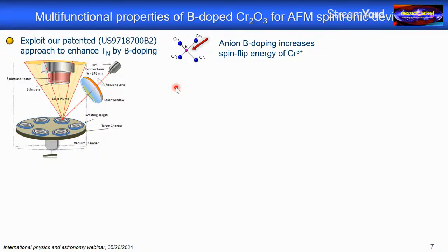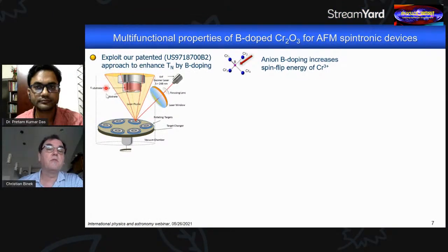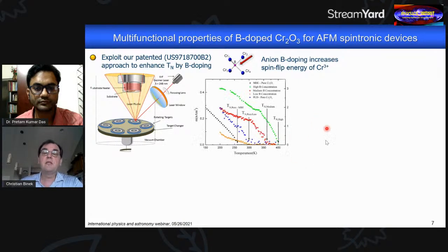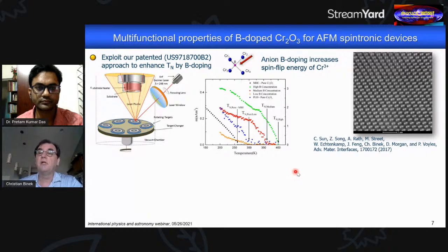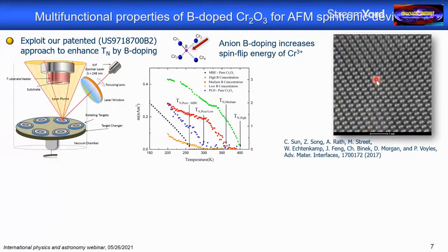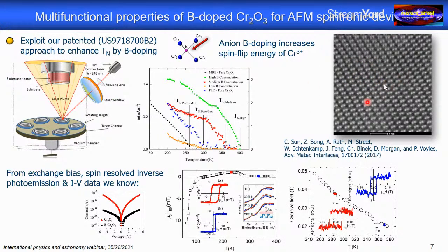We followed this approach, so we grew boron-doped materials by pulsed laser deposition. We start out from a chromium oxide target and deposit in a decaborane gas background. That approach is patented here. And that works quite nicely. Indeed, we were able to increase the Néel temperature. Also nice to see was that the structure of this material did not degrade. Here is a high-angle annular dark field scanning transmission electron microscopy image done by my colleague Paul Voyles on one of our boron-doped samples. And you see nicely this buckled structure of the chromium 3+ ions. The c-axis goes in this direction, and you see this tiny bit of buckling of the chromium ion. So a very nice structure.